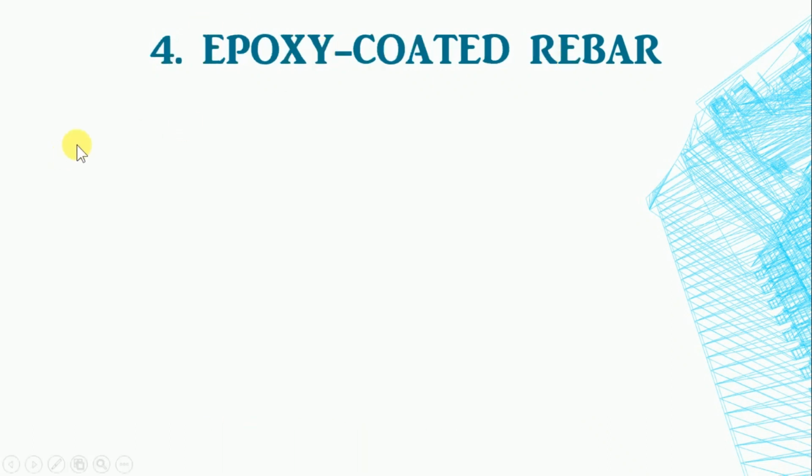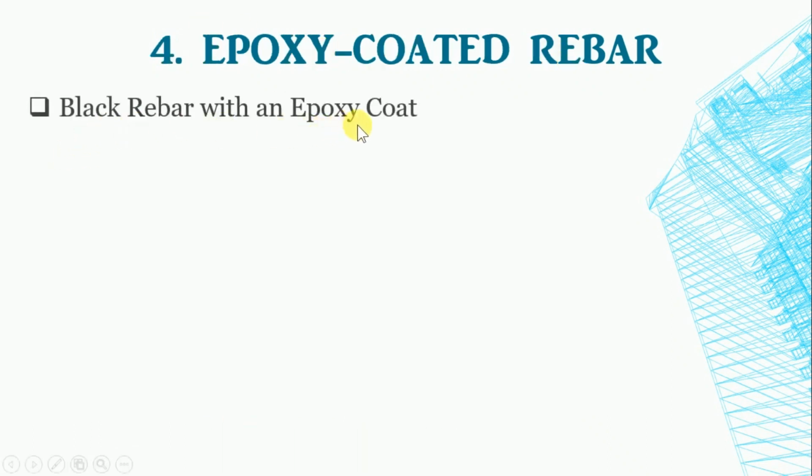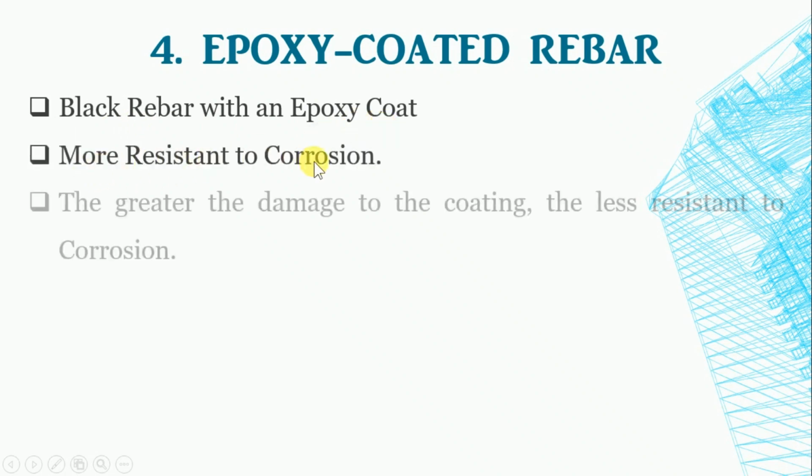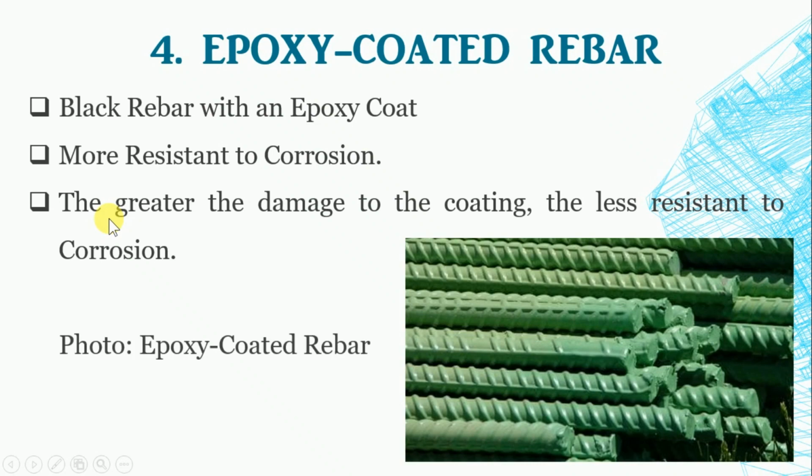Epoxy coated rebar. Epoxy coated rebar is a black rebar with an epoxy coat. It has the same tensile strength but 70 to 1700 times more resistance to corrosion. However, the epoxy coating is incredibly delicate. The greater the damage to the coating, the less resistance to corrosion.